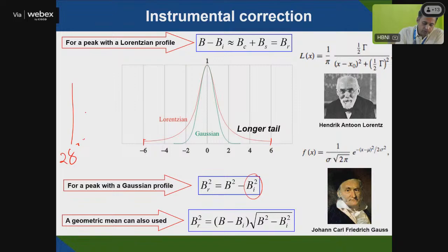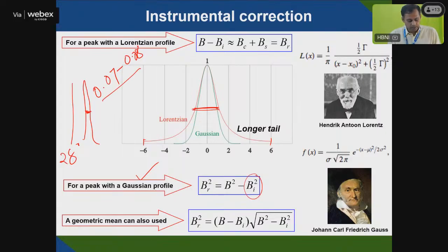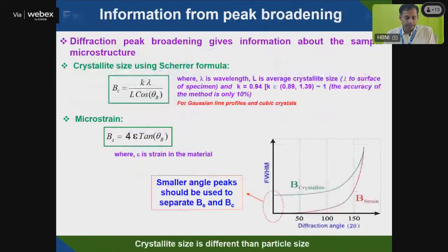If your instrument gives a broader peak instead, that is the broadening due to instrumentation. Generally, you get about 0.07 to 0.08 as the instrumental broadening. You take that width as B, and if it corresponds to Gaussian fitting, you subtract B instrumental from B sample. If it follows a Lorentzian, then you have to use a different type of equation. Once you subtract the instrumental line broadening, you will get a sharp peak.